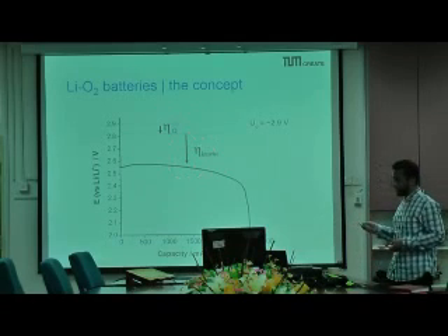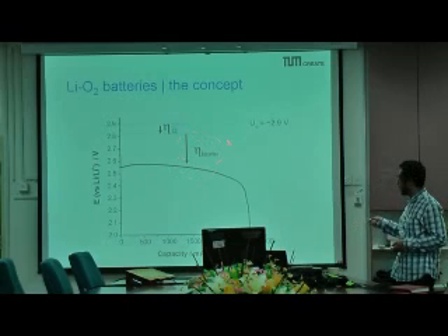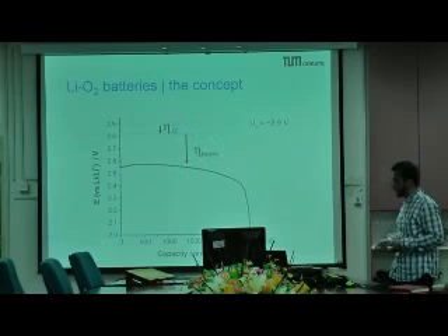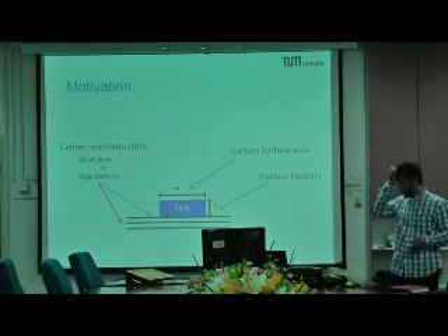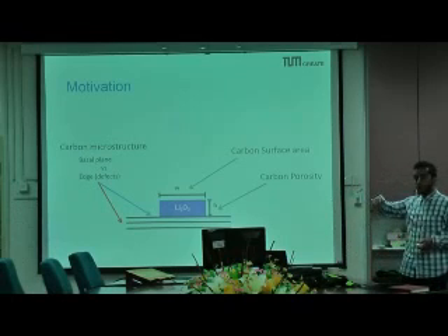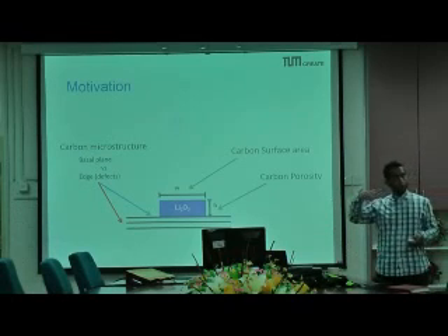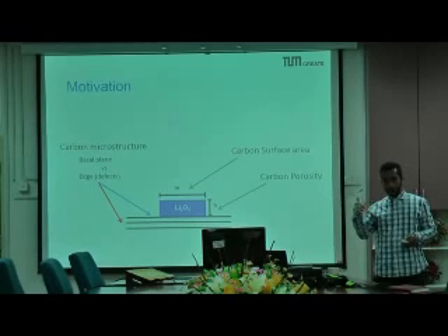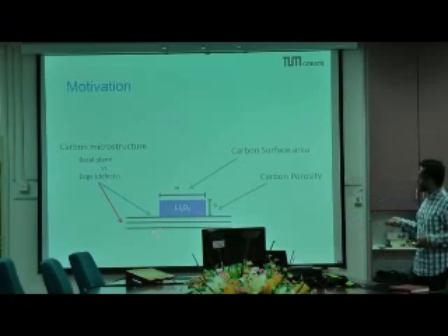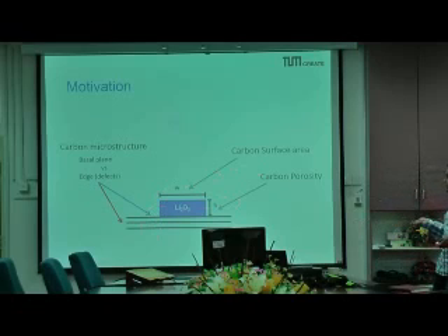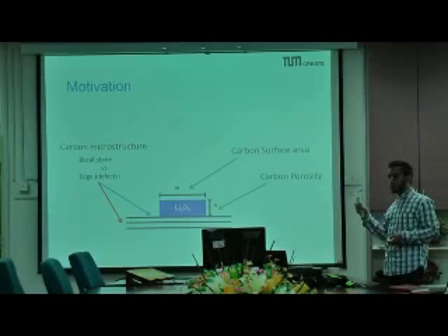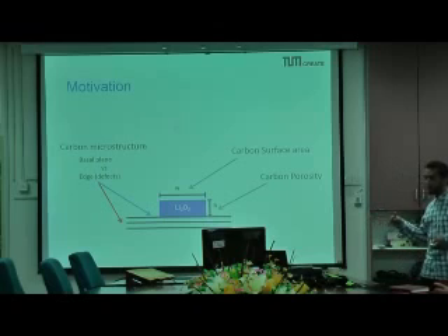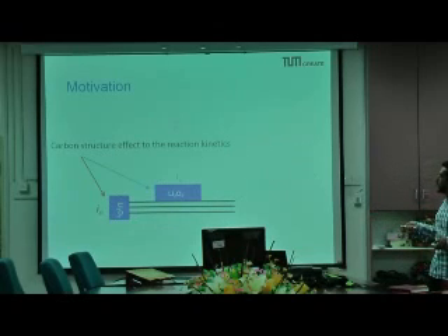In the second part of the talk, I would like to highlight how we change the overpotential of the kinetics. The motivation is that an oxide, a product of oxygen reduction, depositing on a carbon cathode surface will occupy space. The space it occupies represents carbon surface area and porosity. But there's also an important feature that carbon has: it has a basal plane and an edge plane. The surface energy of these two surfaces is quite different, meaning that the kinetics taking place in these two regions can be very different.